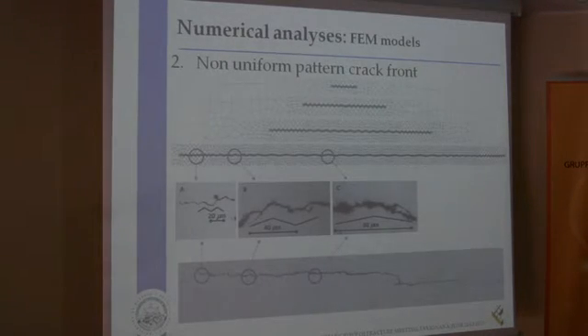Another model considers a non-uniform pattern crack front, which means that the tip slope changes, in particular reduces, moving from the crack tip to the center of the crack, in order to reproduce what we noted experimentally. And we schematize for this aim the crack in different regions having different tip slope.